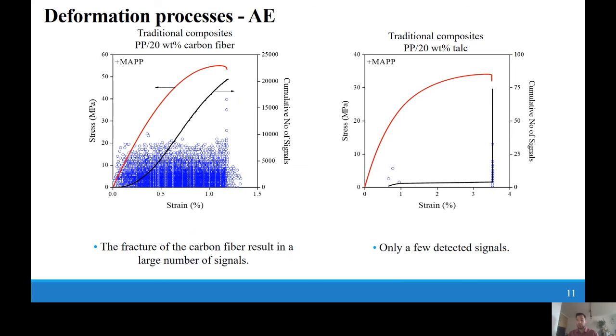In parallel with the tensile test, we also performed acoustic emission measurements. On the slide, the stress versus strain curves and the cumulative number of signals are visible. Each blue symbol indicates individual events that occur during deformation, the source of each signal being some kind of micromechanical deformation process. The location and distribution of the symbols on the figure include a lot of information, and it is difficult to interpret. So we created a cumulative number of signals. This is the black solid line in the figure, which sums up the number of individual events up to a